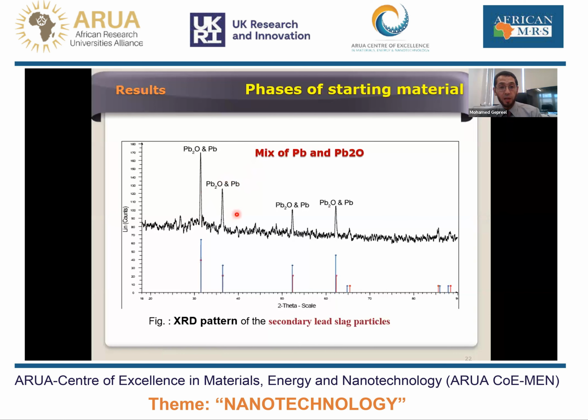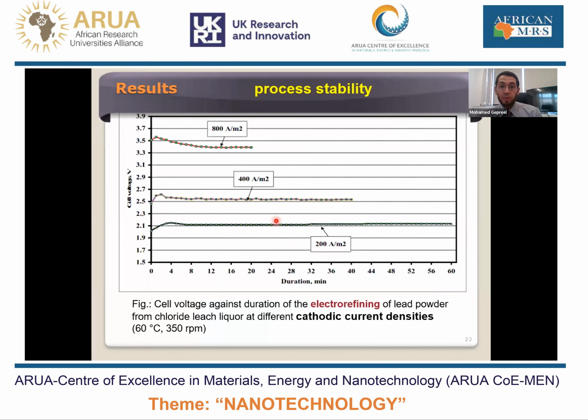This is a mixture of the secondary lead. As you can see by XRD here, it is a mixture of lead oxide and lead. And through processing, we optimize. I won't go deep into the optimization process of the recycling. Actually, regarding the current, we use agitation, temperature, solutions, addition of electrolyte, and so on. Many parameters have been optimized. I just want to put this away, and we can see here that the process is optimized and stabilized.